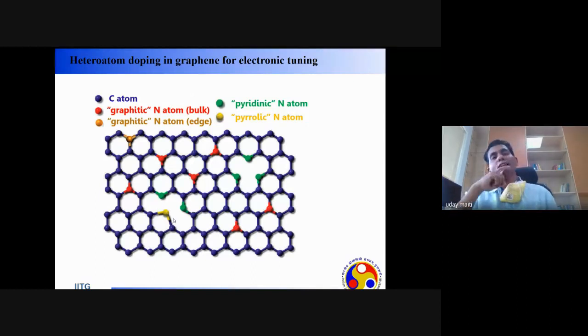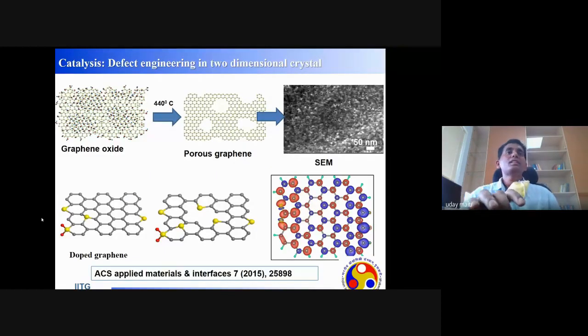So we took this as some kind of theory by which, if we can create some pores, we can incorporate some big heteroatoms. But how to create the pores within a graphene? So we started with graphene oxide. And graphene oxide, as I mentioned, is a functionalized form of graphene. But there were already reports that in graphene oxide, there are some patches, a region where there is no functionalization. This is graphene-like.